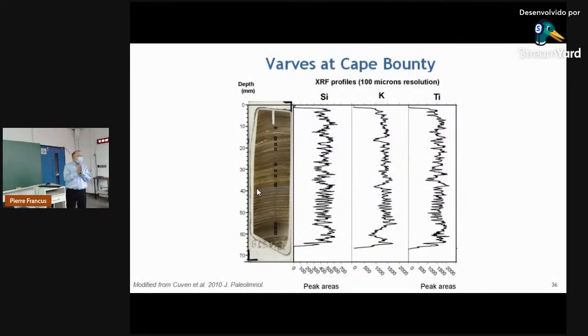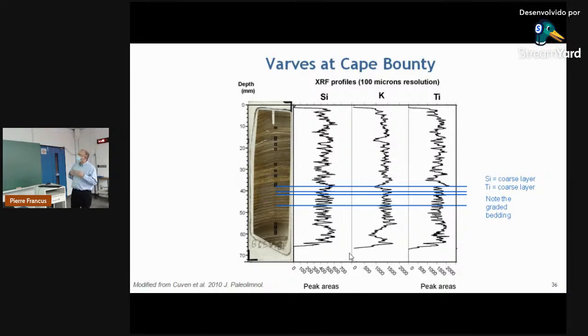So the Varves, these are the clastic Varves. The Varves at Cape Bounty are clastic Varves, and here on the left side you have an image of the Varves, very similar to the one I showed you already before. And on the right side you have the profiles measured with the MicroXRF scanner. You have the profile of silica, profile of potassium and titanium. And if I look at the maximum in the silica and the titanium, which are indicative of the terrigenous input, you can see that the silica and the titanium are always linked to the coarse layer. And here, this is a thicker Varve, you can see the graded bedding, where potassium is inverse to silica and titanium. So the potassium is usually more rich in the clay, so fine sediment is rich in potassium.